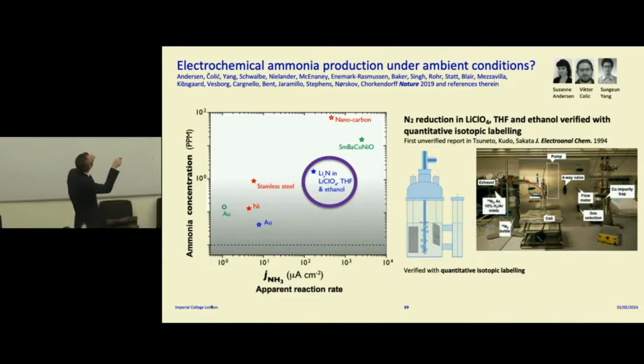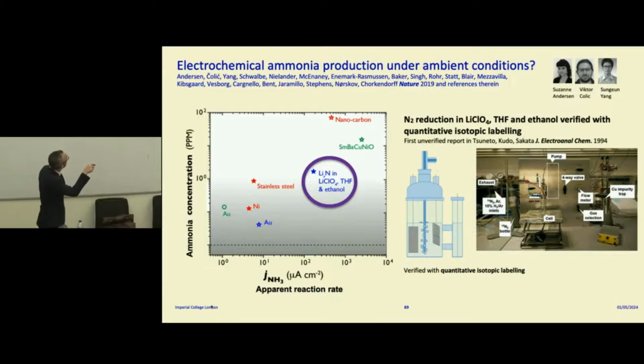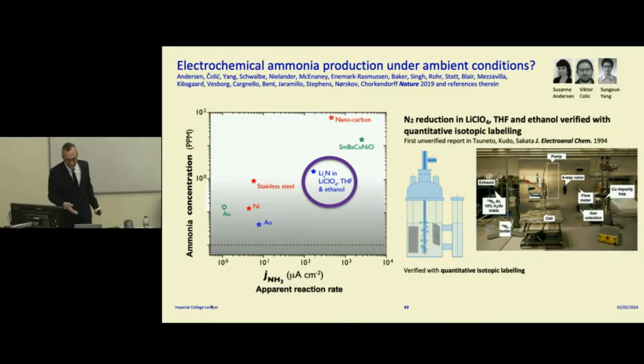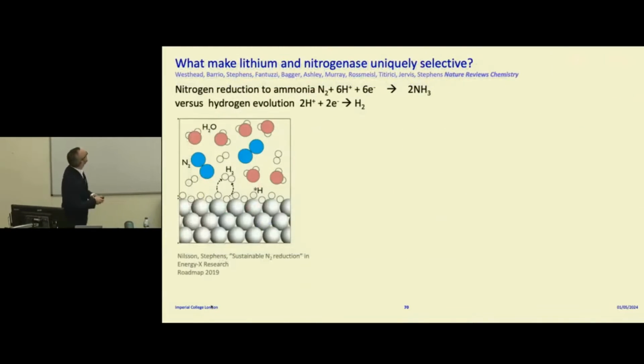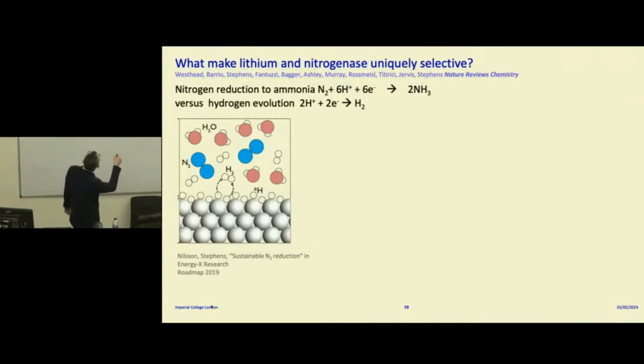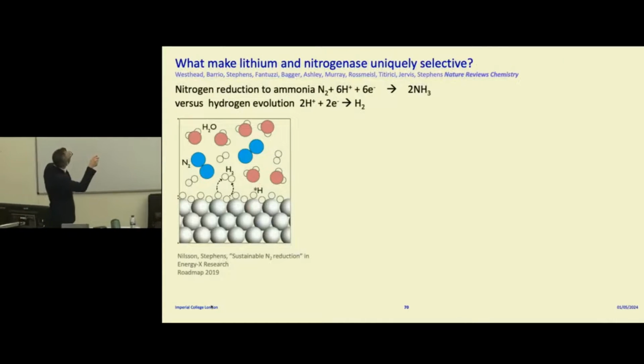So we had a paper in Nature 5 years ago. What we found is that one paper alone, barely cited, from the 90s in Japan, actually works. It essentially electrodeposited lithium in an organic electrolyte, using chemistry very similar to a lithium-ion battery. The challenge in doing nitrogen reduction is that you've got a competing reaction with hydrogen evolution. So nitrogen, these blue atoms here, is very inert, and hydrogen is a lot more reactive. And typically, hydrogen will bind to the surface and stop nitrogen from getting there.